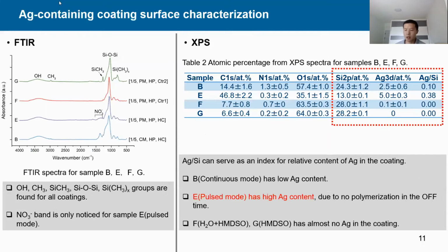We use FTIR to check the functional groups in the coatings. Most coatings give similar functional groups. Only with sample E, we can see a weak band from nitrate, which suggests the retention of nitrate in the nanocapsules.